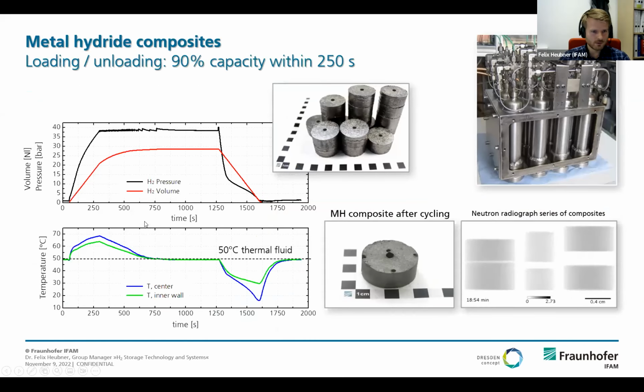Just to show you one example about the dynamics of a titanium manganese based material during hydrogen absorption and desorption. Here on the left-hand side of this slide, you can see the temperature of the experiment versus time. And here on the upper part, the pressure in black and the volume in the red curve. So pressure is increasing for refueling of the materials, so loading the materials above some kind of an equilibrium pressure where the hydride formation takes place. This was here something like maybe 20 bars, so we increased pressure until 40 bar.